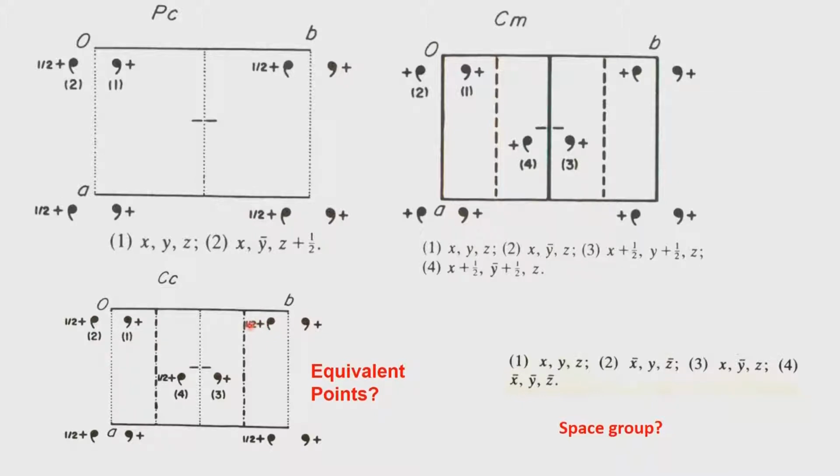Now, what you see here is that by definition, whenever there is a symmetry operation at 0 and the symmetry operation 1 unit translation, the same symmetry operation will develop at half position. So, using this half position, the C glide, we can generate its corresponding C glide operation. So, that means this now goes into a mirror symmetry, and then it adds on a half in the direction of C, and therefore, we get to this point 4.